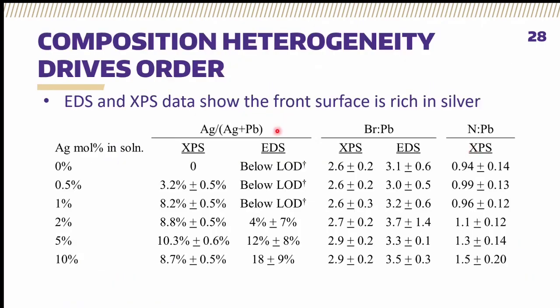To figure out exactly what was going on, we turned to composition heterogeneity as an answer to our issues, with the idea being perhaps silver was somehow changing the relative surface energy of different facets. To first examine this, we took XPS and EDS, two different elemental techniques, of all of our different silver mole percent inclusive MAPbBr3 thin films. And this is important because these two techniques have different penetration depths and therefore probe different parts of the film.